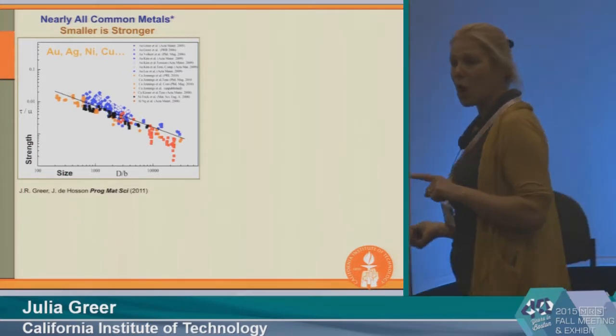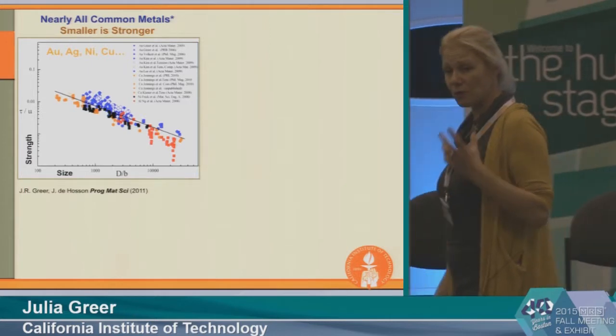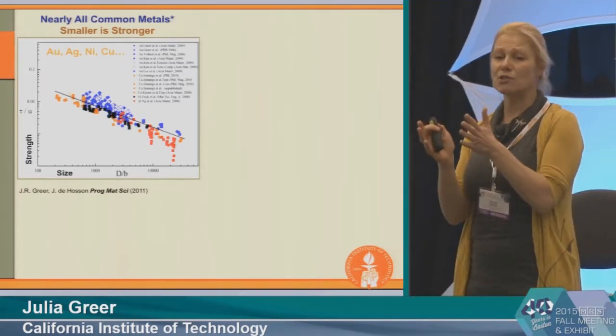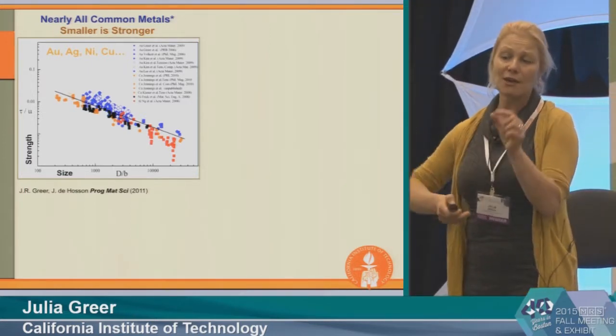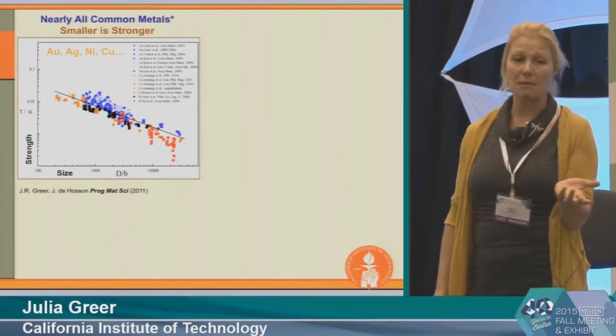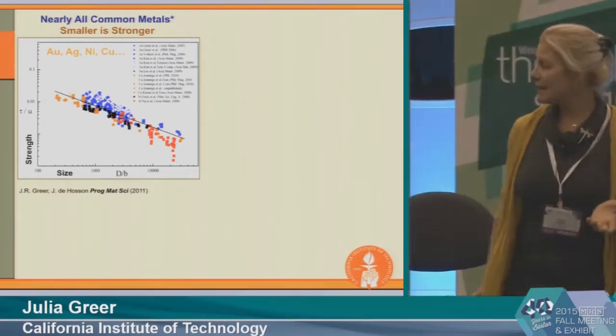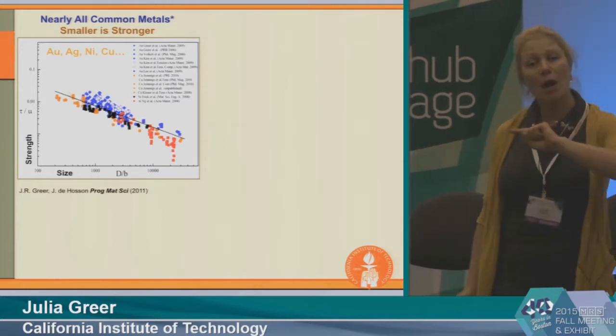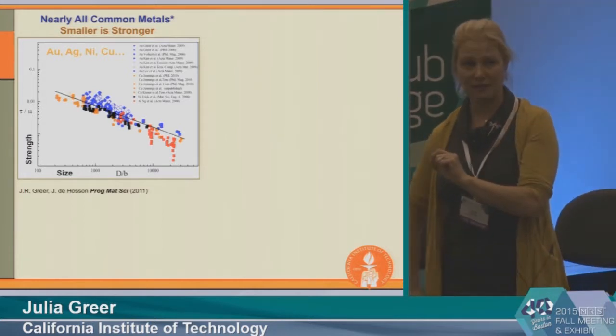So yet again, this is a log-log plot. This is strength as a function of size. So when you reduce the dimensions of a single crystalline metal down to the nanoscale level, or at least micron and submicron level, they exhibit this smaller, stronger size effect in a power law fashion. This is a very strong size effect. Okay?